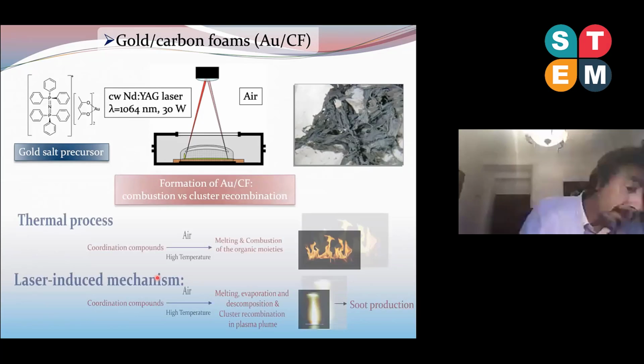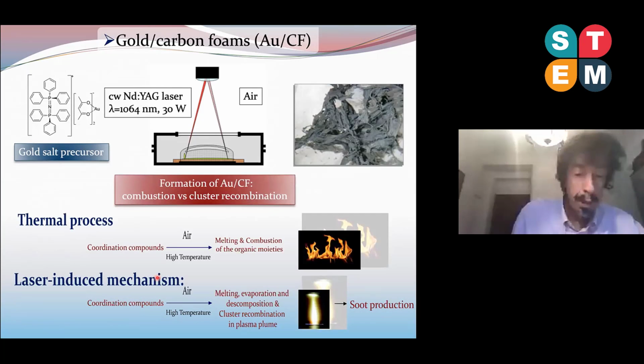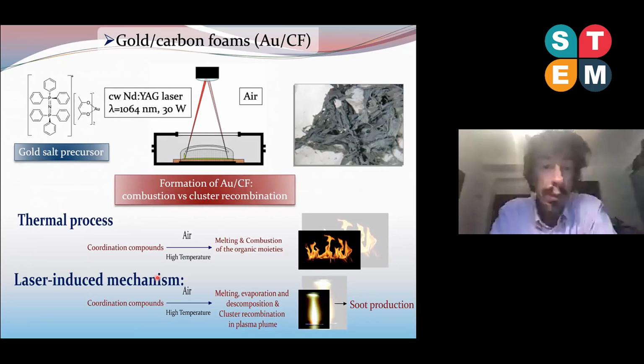We expected at the beginning that we were going to get a thermal process, so we would burn all the organic moiety, but instead we got the formation of soot. And this is because this is a laser-induced mechanism where there's cluster recombination of very reactive species in the generated plasma plume. So we got the production of this kind of soot, which is common for many kinds of laser ablation synthesis methods.